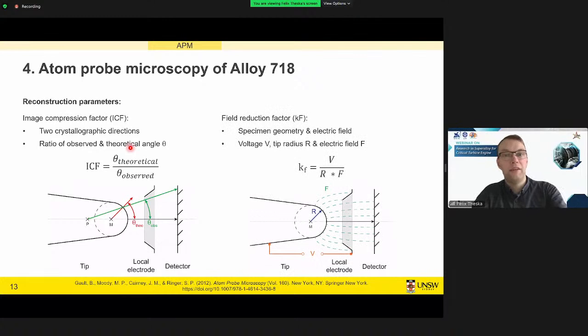On the other hand, we have the so-called field reduction factor. And that's a bit more complicated because it depends on the specimen geometry and the resulting electric field. And often the exact specimen geometry is not known, so we can only approach this factor as close as possible. But that's then calculated from the voltage, the tip radius approximation, and the measured electric field.